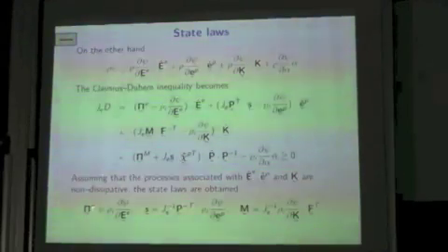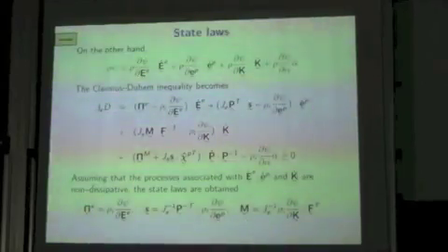You plug it into the Clausius-Duhem inequality, and you can postulate some hyperelastic constitutive equation. The usual one, the Piola-Kirchhoff stress on the intermediate configuration, so hyperelasticity is a standard one, and I postulate also hyperelastic relationships with respect to the curl, the dislocation density tensor, and here the double stresses.